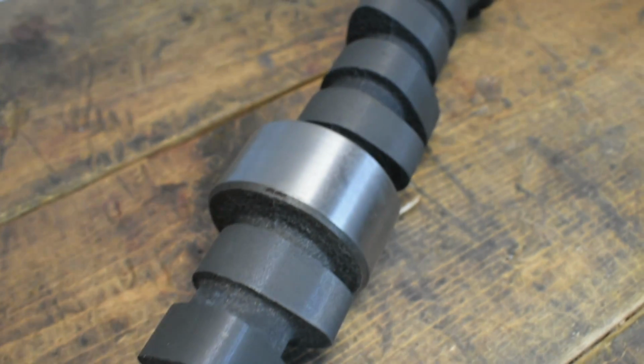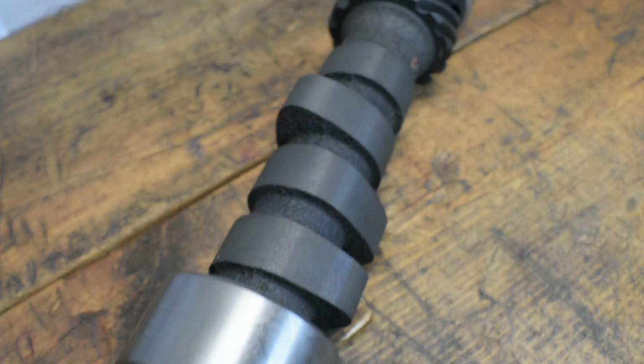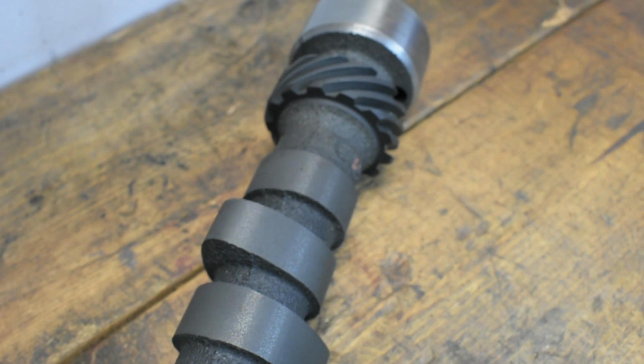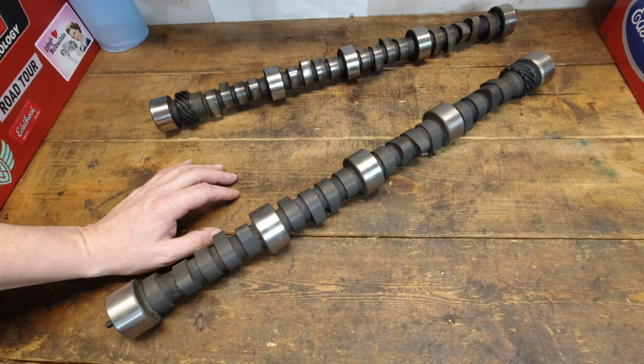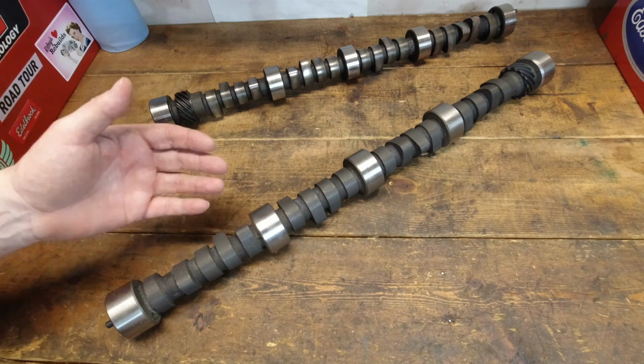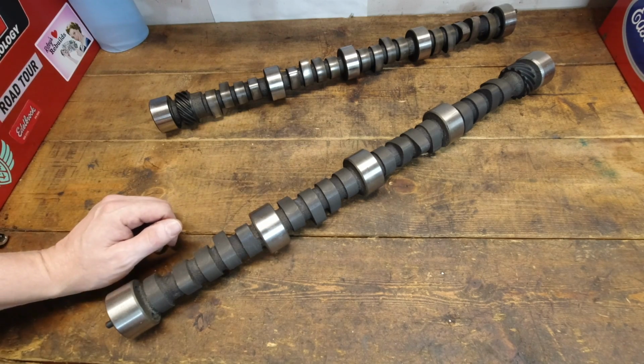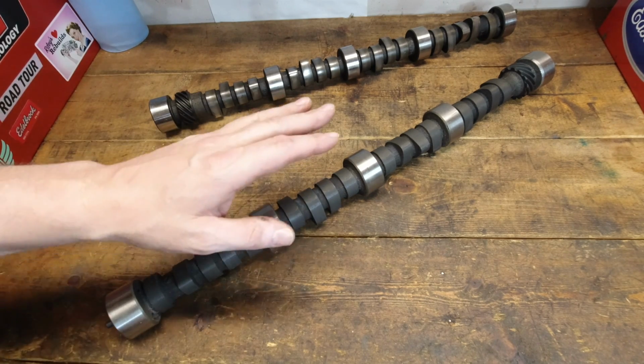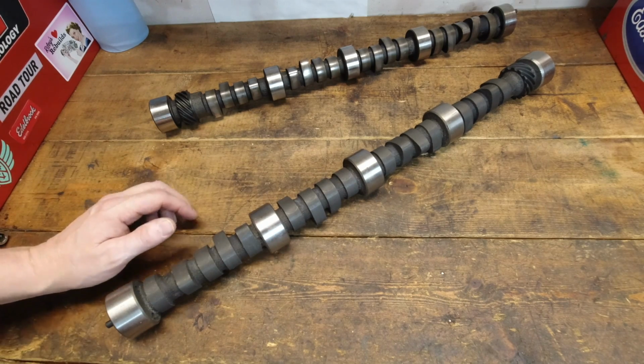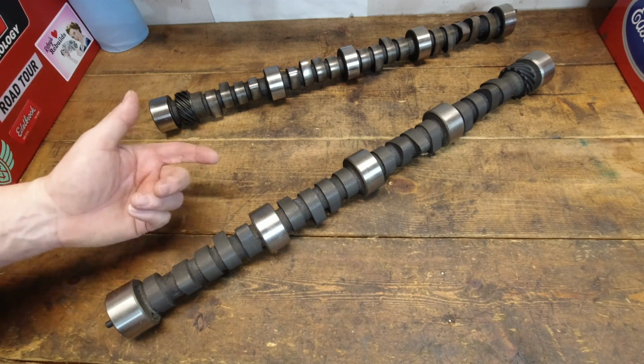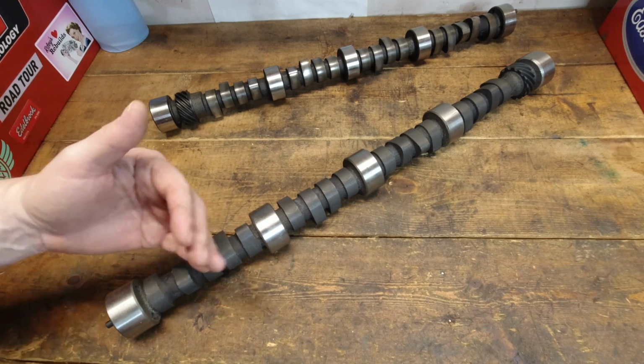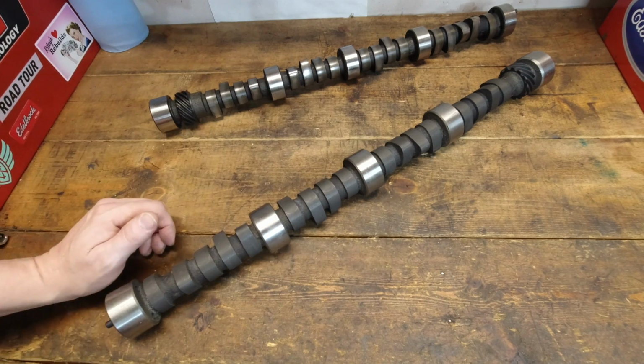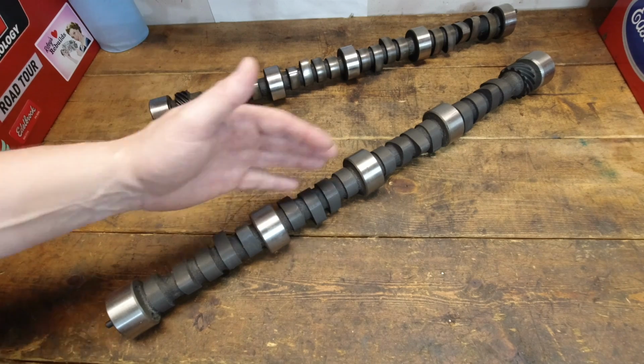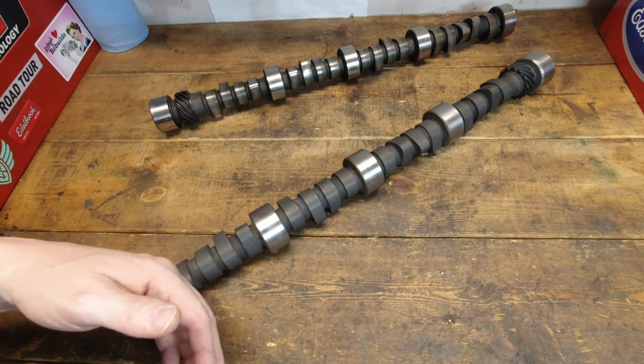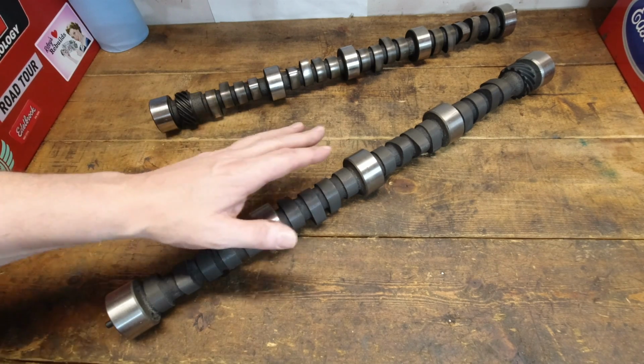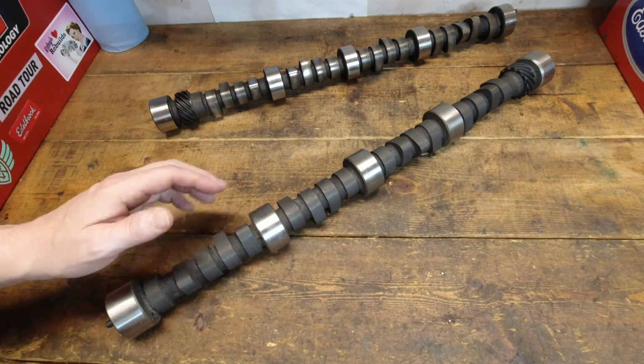Now, I can't speak for every camshaft manufacturer out there, but I can tell you that, with the number of failures that they have, they need to be able to Rockwell test that before they even start doing anything. So if they order 100 of these camshafts, the first one that comes out of the bin is probably going to get tested or it's going to get cut apart. I'll show you that here in just a minute, to verify the depth of the heat treat. That way they know that the other 99 that they're going to grind are going to be at the heat treat depth that they need.